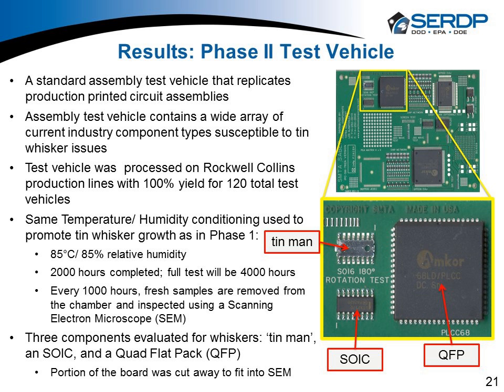The reason this was important is, of course, Tinman is going to do everything it did in phase one. But in phase two, when you solder, you tend to get a lot of solder up on these leads, and it self-poisons the lead. It's one of the mitigations the industry uses. That way, we didn't expect to see any whiskers on this because of soldering. This quad flat pack, you can imagine, solder doesn't run all the way to the top of the leads. The leads are too tall. So we thought we might have a chance to see and record some whisker behavior at the top of the lead.